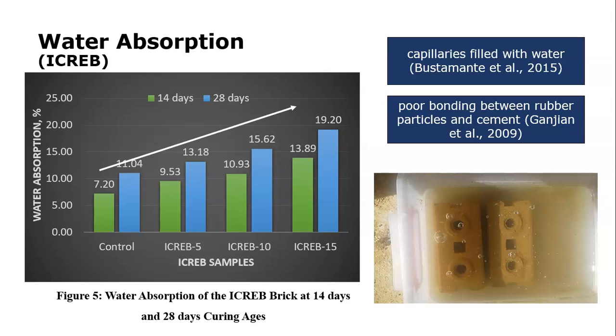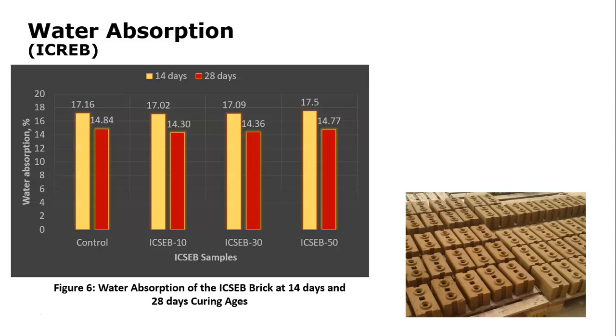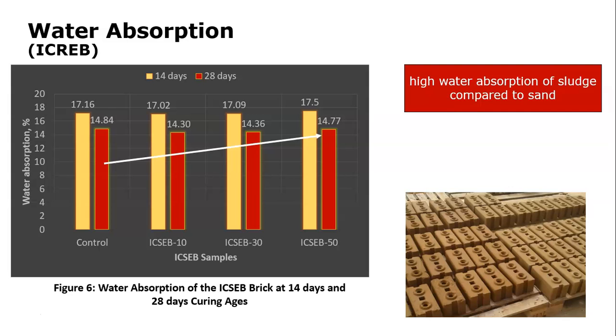And as shown in figure 6, okay, the water absorption of the ICSEB bricks is also increased as the percentage of the sludge replacement increases. And this is possibly due to the high water absorption of sludge compared to sand, which results in an increase of the brick porosity and finally causes a high water absorption value compared to the control brick.